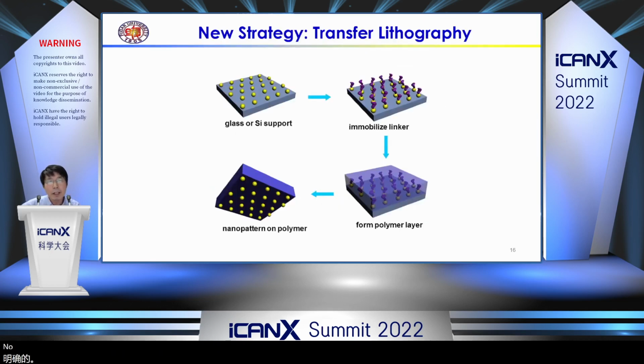Now, what I would like to give is a very brief idea of the basic idea of our material technique. Because it is almost impossible to link an RGD array directly to the PEG hydrogel, we put forward a transfer lithography technique. We prepared the gold nanopattern on glass and used the immobilized linker to form a polymer, and then we transfer the pattern to the polymer.